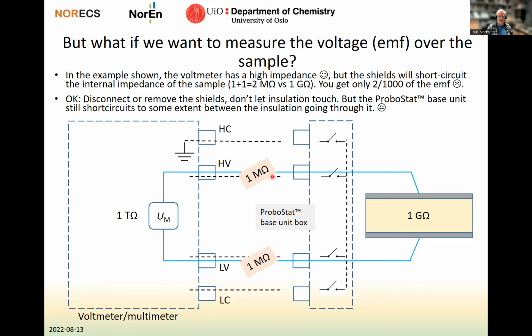And if the shields are connected together, you get typically, let's say 1 plus 1 is 2 mega ohm, and that will efficiently short circuit the 1 gigaohm sample. And the EMF you measure will only be 2 promille of what it should have been. The voltmeter does not take care of this. Okay, you can solve that by disconnecting or removing the shields, so that, as I have done here, they are not in contact with each other unless they are contacted with a chassis here. So in principle, this could go well.